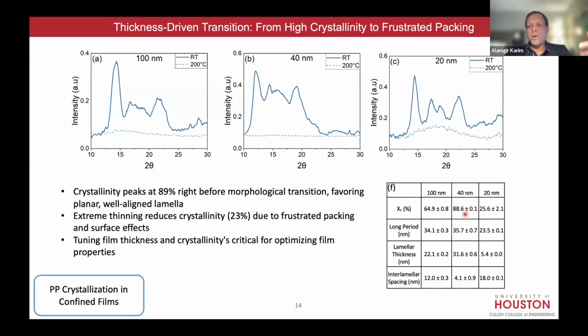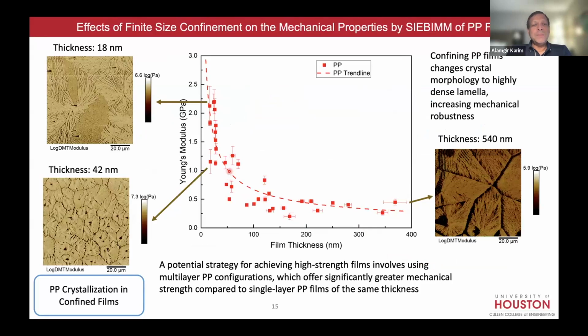Okay. So there's an optimum window of aligned and high degree of crystallinity. And so you can expect the modulus can go up. We also measure long period and so on, interlamellar spacing, etc., as you can see. All right, just to show you, we measure with the SIEBIMM technique. SIEBIMM is a strain-induced elastomer buckling instability measurement method. As I said, you take a PDMS elastomer, stretch it, put your polymer, glassy polymer or semicrystalline polymer, PP film, let it go, it will compress it. You'll see the wrinkling wavelength, and we have an equation to calculate the Young's modulus, bending modulus. So you can see the modulus is significantly enhanced in ultra-thin film compared to the thicker, half micron kind of film because of morphological changes. I think the steep upturn happens when the lamellae orient because of confinement, in the film thickness direction.